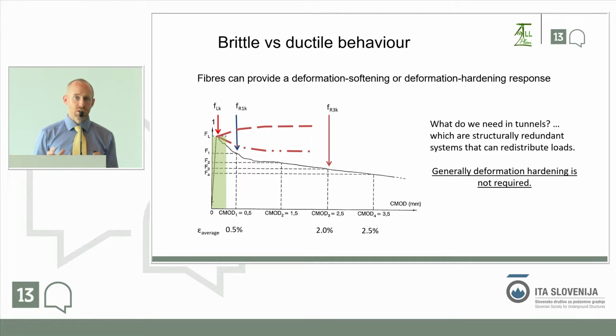So, turning to the structural side, a lot of you are familiar with this sort of picture from a simple beam test, where you take a beam, you bend it, the concrete cracks, and then you have this residual tensile behavior, and it can go up, which is called deformation hardening, but more typically you'll have a peak, it drops, and you have a deformation softening.